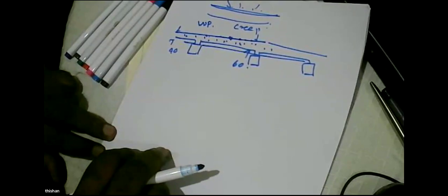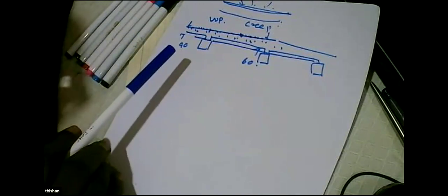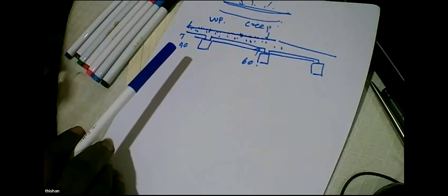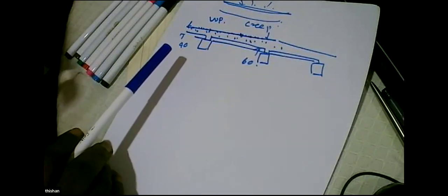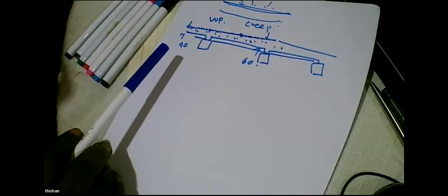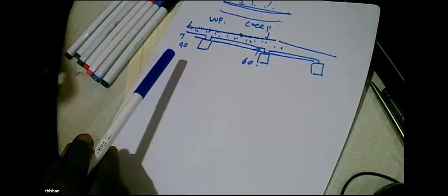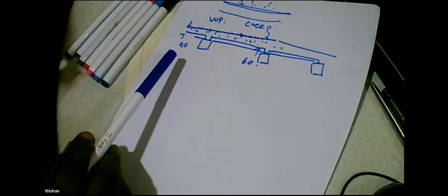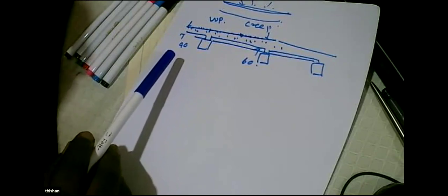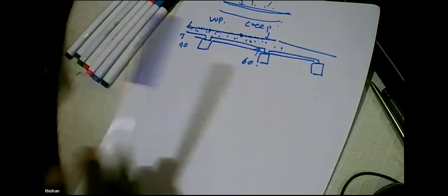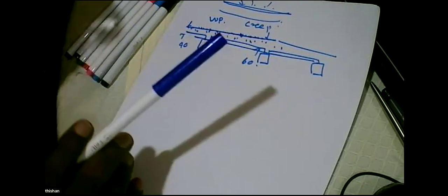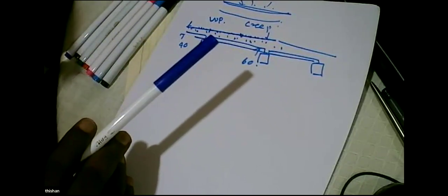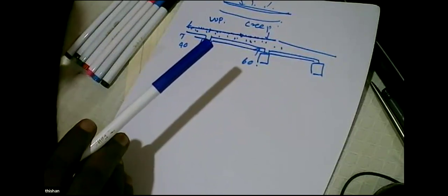So there are so many things you can do, because the whole idea of embedding chips here is that, rather than having a concrete cement-based surface, what is exposed to the rain will be a chip-based surface. And we know chip-based surfaces are much harder and more erosion resistant than concrete-based or cement-based surfaces. So the whole idea is we spread a pre-prepared mix of pebbles, marble pieces, terrazzo chips, you name it. It can be glass chips, anything. That is hard materials. And then use a float and firmly embed those things into the fresh concrete.